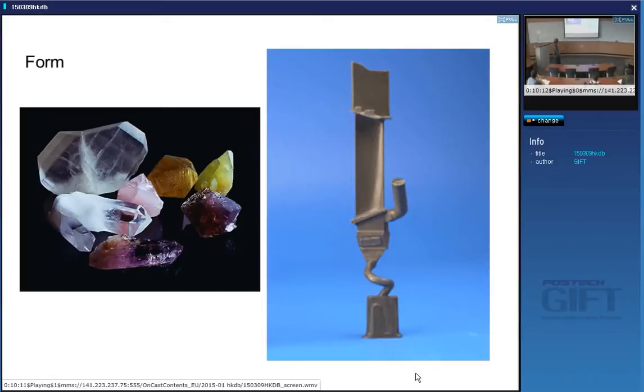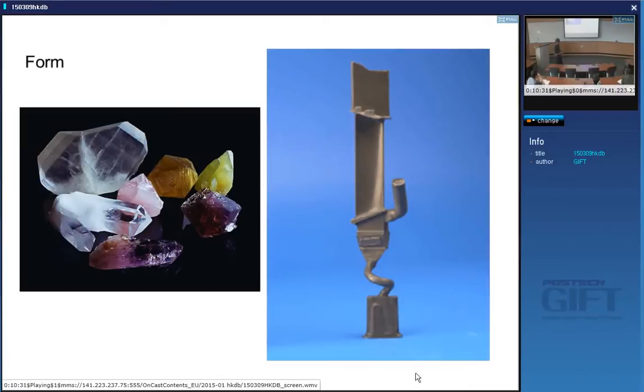You start solidification from one end in a temperature gradient, so you get lots of crystals growing in that direction. The one growing fastest fills up the spiral selector and blocks all the others. Therefore the rest of it solidifies as a single crystal.